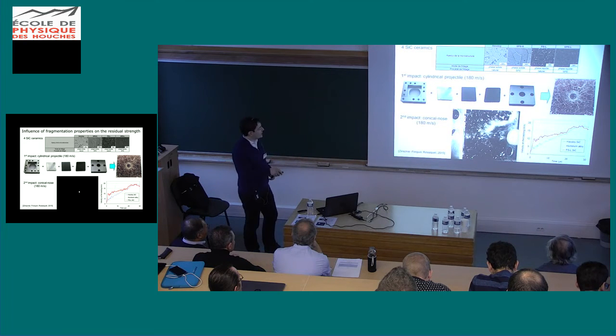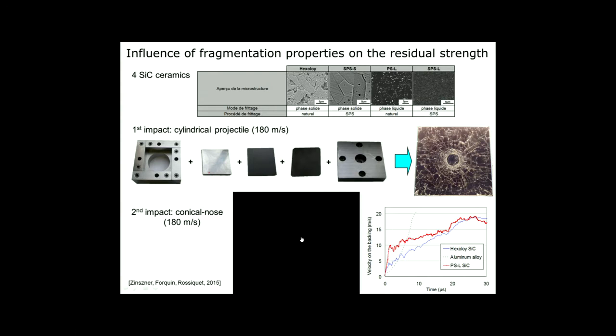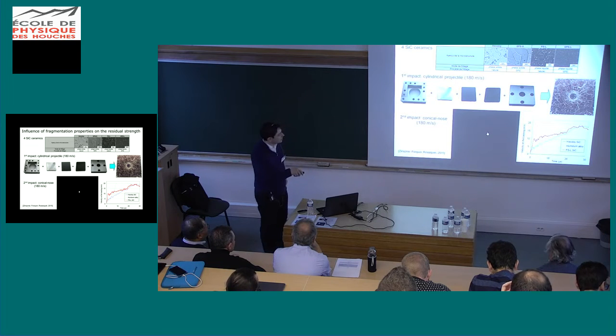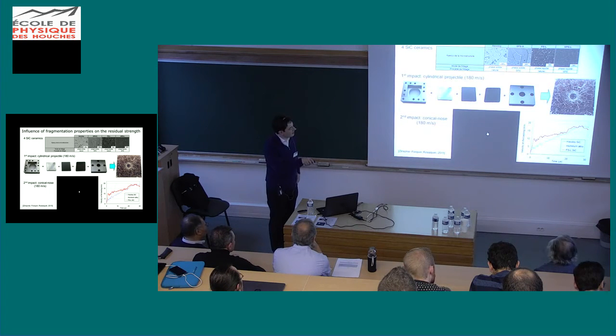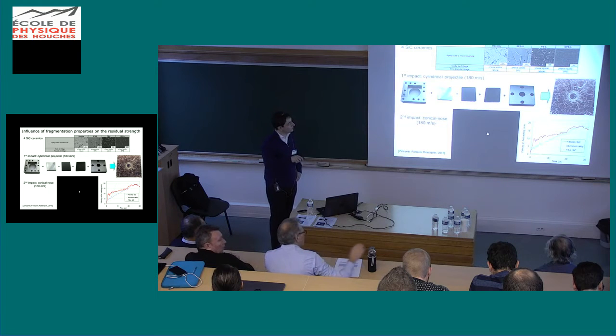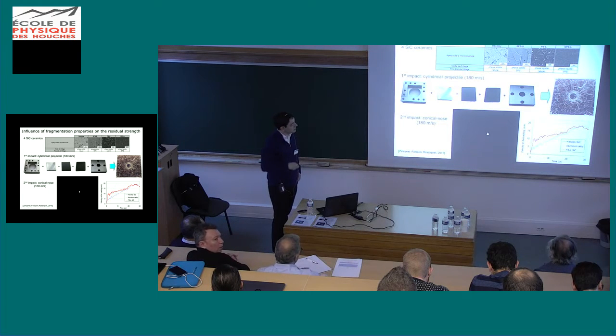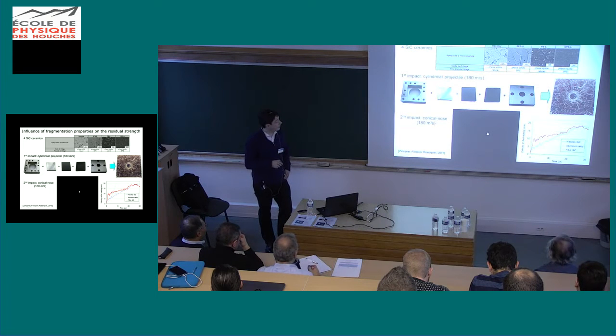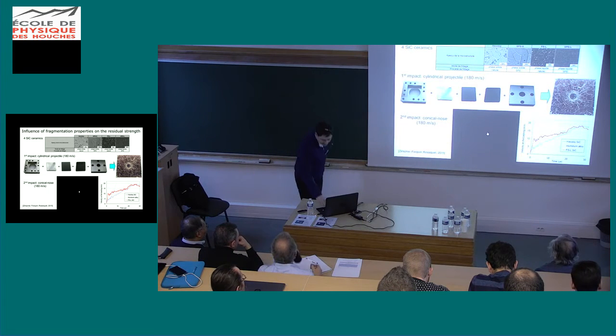And after, it was re-impacted with a conical projectile, as you can see. And what was observed since the Zinszner PhD work was that the velocity profile was strongly different depending on the fragment size in the ceramic target. So there is a relationship between fragment size and the penetration resistance of the fragmented medium. That's why we need to analyze and better understand the fragmentation property of this kind of material.